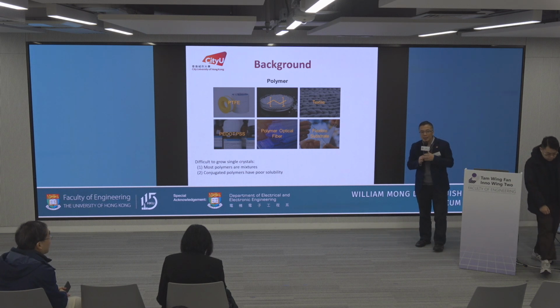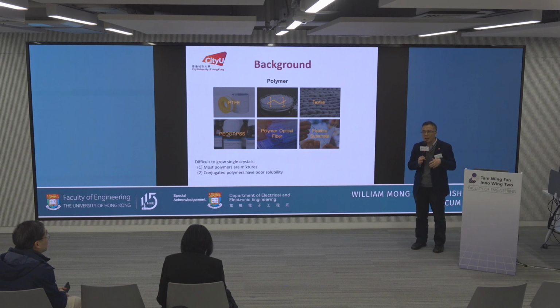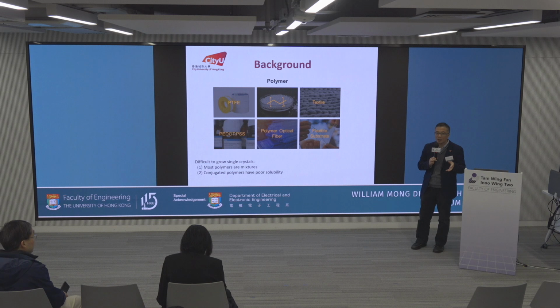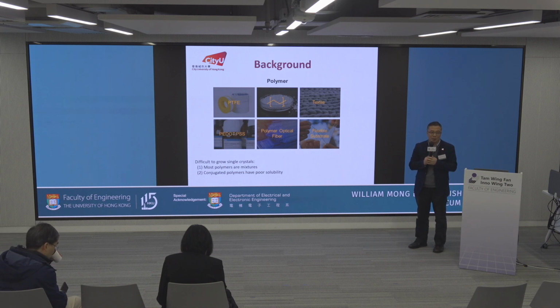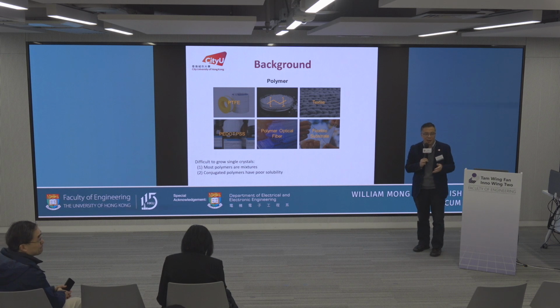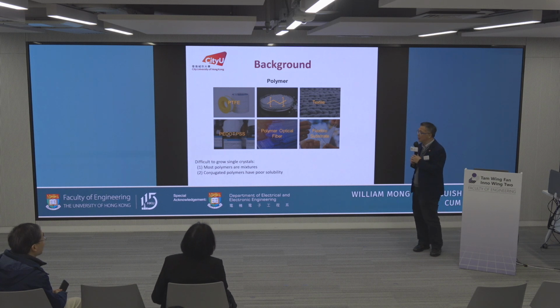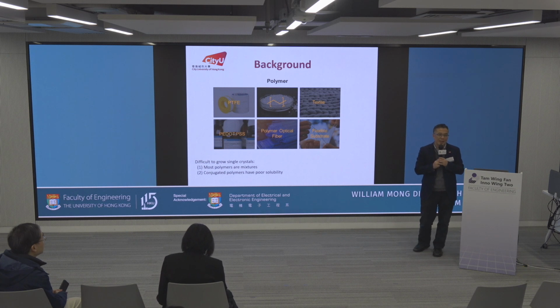Now the question is, not all polymers can meet our requirements, so sometimes we need to modify the polymers. How? Now we have a big issue. When we try to introduce a functional group or functional atom, where do we put it, and we also don't know how the polymer chains stack in space. The reason is that knowledge about polymer single crystals is much less, right? So here we have a big challenge to grow the single crystal.